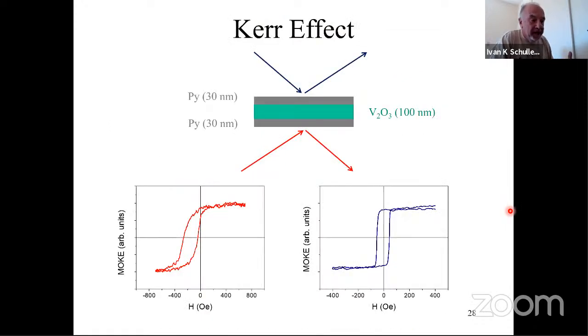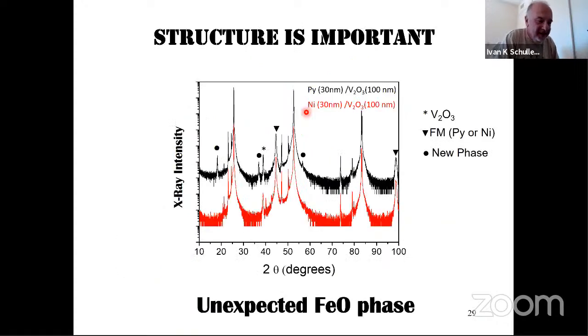Because if you grow the permalloy, then you grow the vanadium oxide, and you grow another layer of permalloy on top of it, if you look at the lower layer, at the lower interface right here, you can do this optically, with what is called a magneto-optic Kerr effect, then you see the hysteresis loop is shifted to the left and shifted outwards. But if you look at the upper layer, that is also coupled to the very same vanadium oxide, it is not shifted at all. Now, at the end of the story, it turns out this is a red herring.